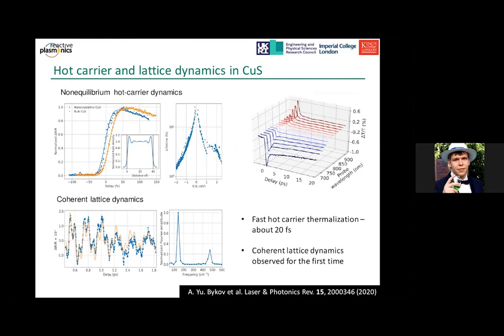In the picosecond timescale, we observe all the standard stages of photoelectron decay, like the emission of phonons. However, our main advantage here is that we were able to tap into the initial non-equilibrium stage of the decay, which was shown to be very fast, less than 20 femtoseconds, comparable to graphene, and even shorter in the nanoparticles compared to bulk crystals, all in agreement with the theory, which is very advantageous from the point of view of applications for ultrafast switching, for example.